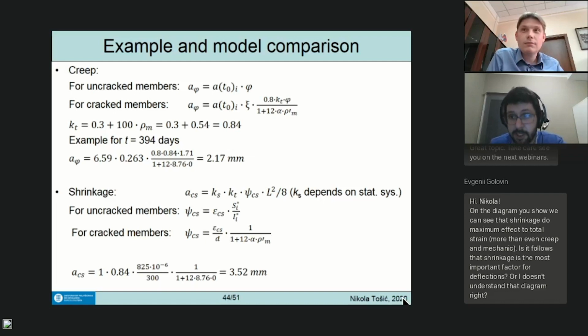Yeah, but it will depend on your reinforcement. As I said, the strain has a high impact, particularly in this case because the value was 0.83 per mille with a very small corresponding creep coefficient, which was a bit strange. If you recalculate, you'd get a much higher creep coefficient, and the values would be more comparable.